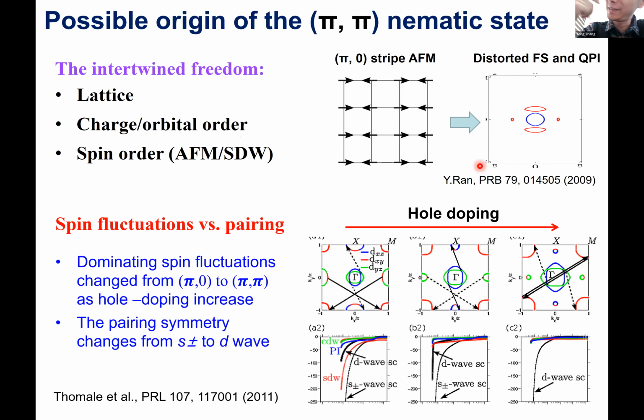So for the possible origin, recently there are several theoretical papers suggesting there could be different origins. Actually, I don't quite understand, but I think some of the authors are here, so we can have a discussion. But I know the pi zero nematicity is closely relevant to the stripe AFM, so it can distort the Fermi surface and give you an asymmetric QPI pattern. And for the hole doped system, in this paper, they predict that the spin fluctuation changes from pi zero to pi pi. I think it may be an origin of such a pi nematicity.